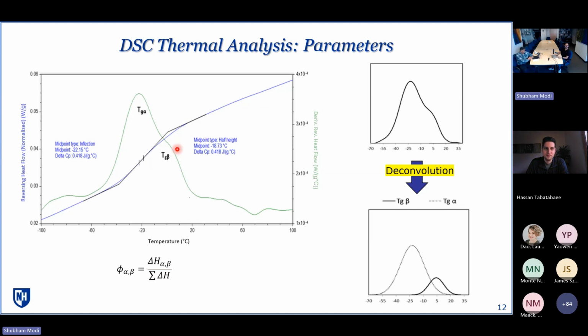Yeah. So here is the typical heat flow diagram generated from the DSC testing, and this is the first derivative of it. Here we can see that this first derivative curve is assumed as a combination of two curves, having the primary curve and secondary curve. The primary curve is more related to the virgin binder, which gives the glass transition temperature on the more negative side, whereas the secondary peak is the contribution from the RAP binder. And the higher the phase separation between these two materials, the broader this graph will be. So for higher or better compatibility, we want this distance to be as minimal as possible.